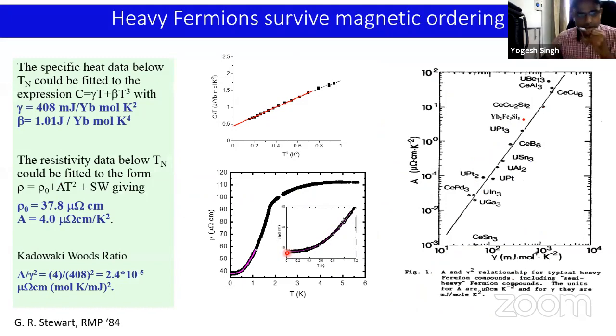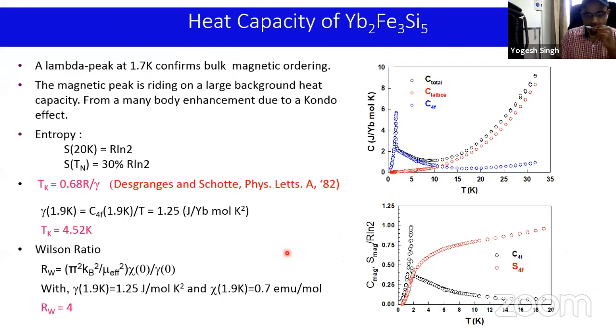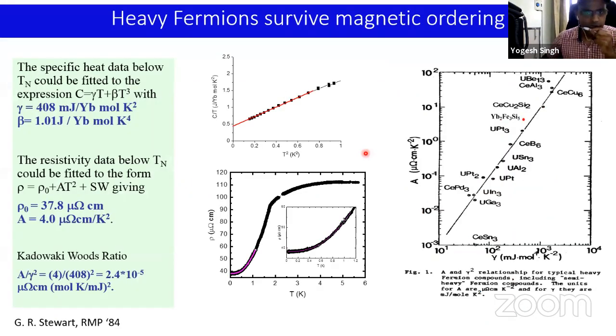So what happens? This is, of course, at just above the ordering temperature. It's a very heavy Fermi liquid. You can see that the gamma is about a joule, which is huge. What happens at low temperatures? Because beyond the ordering, do the heavy fermions survive? So we show here the C by T versus T squared, and the low temperature indeed extrapolates to again a large value of about 400 millijoules.